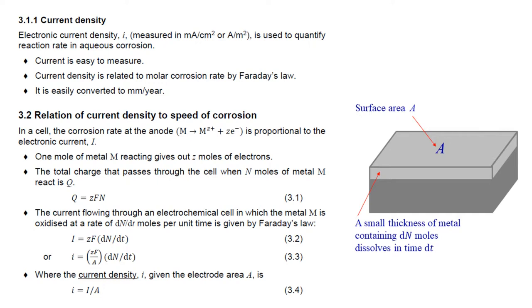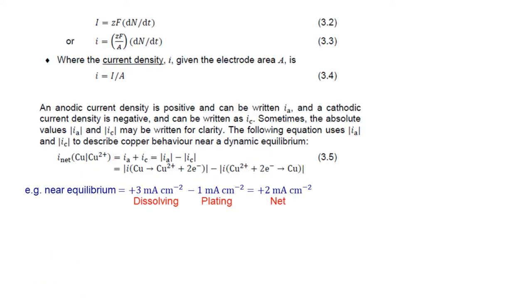Now, the electric current is the rate of flow of charge, so we can just differentiate equation 3.1 to get equation 3.2, in which the total electric current I is given by ZF dN/dt. ZF is a constant for the given chemistry, so we're just differentiating the number of moles N which have dissolved to get this molar rate of dissolution dN/dt. We can say that the net corrosion current density, then, is this small term i in equation 3.3. It's just the current per unit surface area of the dissolving block, as shown in the picture. Now, since the metal here is dissolving, it's an anode, and we conventionally say that current density for an anode is positive. So, like, plus 3 milliamps per centimeter squared, for example.